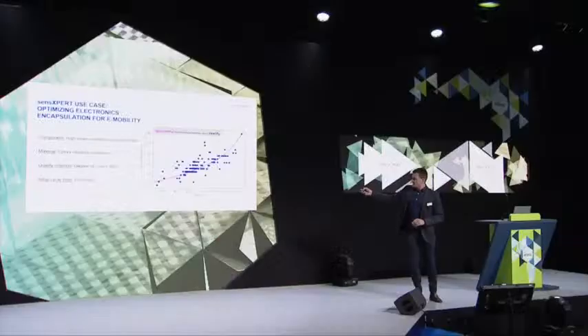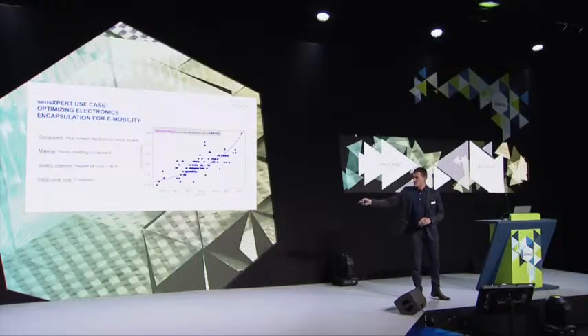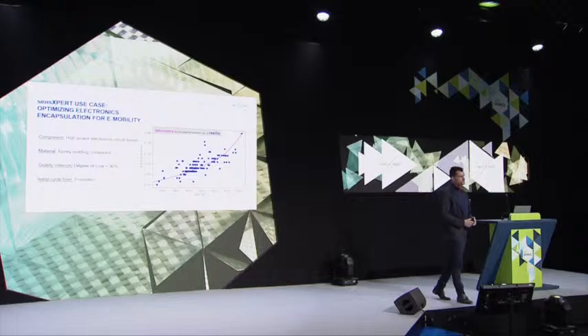In this case, you can see, ZF initially manufactured the components with a cycle time of 3 minutes in a multi-cavity mold. 3 minutes was for ZF the balance between component quality and shortest possible cycle time, while knowing that they have a lot of safety times on top because the material deviates and they need to make sure that the scrap amount is as low as possible.